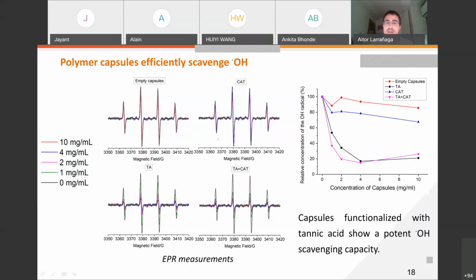I will not go into the detail of this specific technique, which is quite complex, but as you can see in this graph on your right, we found that those capsules that were functionalized with tannic acid were able to reduce the levels of hydroxyl radicals from the solution, suggesting that this combinatorial approach, by combining the catalase inside and the tannic acid on the surface of our capsules, is a valid strategy to scavenge more than one reactive oxygen species that will be really important to provide antioxidant capacity to our capsules.